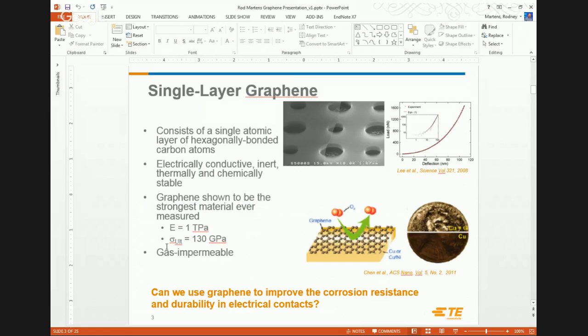So they're fantastic mechanically at those levels. It's electrically conductive. Lots of people are looking at it for, can we make transistors and other things out of it? Certainly beyond the scope of this talk. And then it's chemically inert and gas impermeable. And from my perspective, that's what really struck a chord with me: are these some properties that we could actually integrate into our products and make them better? So just a little example on the right there with a penny that was half coated in graphene and exposed to a corrosive environment. You can see that the upper half of the graphene is still shiny, and then the bottom half looks like a corroded, oxidized copper penny.